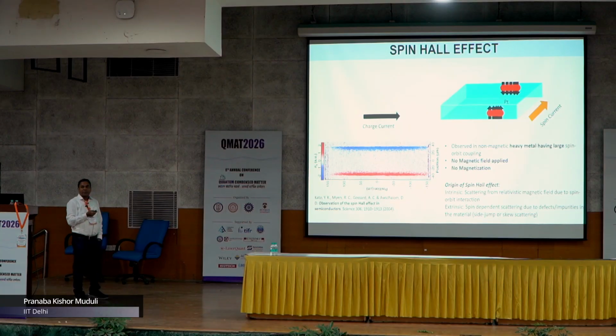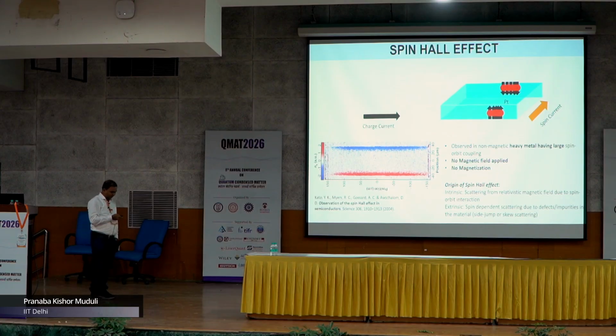And the origin of the spin Hall effect is basically related to two kinds of origin, intrinsic and extrinsic. The intrinsic is coming from the band structure, where the scattering from the relativistic magnetic field due to the spin orbit interaction drives this effect. Also there are extrinsic effects due to scattering, similar to AHE, such as side jump and skew scattering.